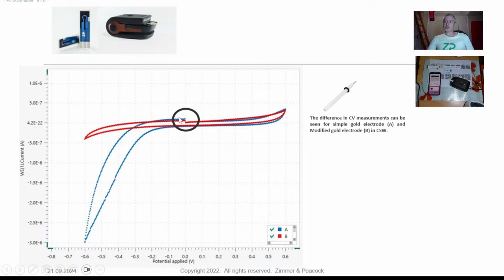You get this discontinuity because here the operator said, okay, start the voltammetry at 0 volts, scan up, and scan down. That discontinuity is because you've started the experiment at 0 volts, and there is actually some electrochemical activity at that 0 volts. If you told the potentiostat to start at open circuit potential, then you probably wouldn't have had that step. I'll show you that we also get that step in our data as well.